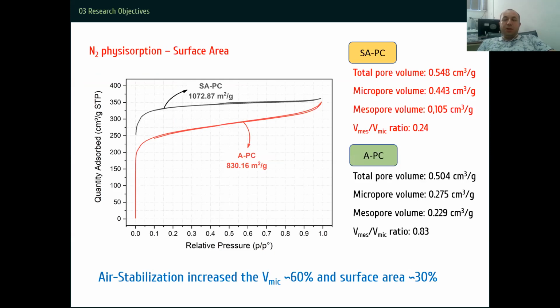The APC sample has a surface area of 830 meters square per gram, while SAPC sample has almost 1100 meters square per gram. The total pore volume and micropore volume have increased in SAPC sample. The mesopore volume to micropore volume ratio has significantly decreased with the stabilization process. The BET surface area of the SAPC sample is almost 30% more than APC sample, and the micropore volume has increased almost 60%, as you see.